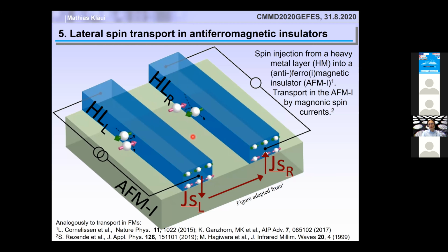And so what we have here is a device where we have a heavy metal on top of an antiferromagnetic insulator, and we inject from this heavy metal spins into the antiferromagnetic insulator. They are then transported in the antiferromagnetic insulator, and then they're absorbed at the detector, and by the inverse spin Hall effect then read out as a voltage. So this was first pioneered for ferromagnets in the group of van Wees, and there are also some reviews here, and we then did this for antiferromagnetic insulators.